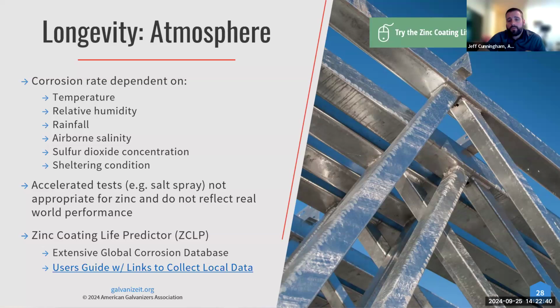We don't have to worry about salt spray testing. Salt spray testing doesn't actually reflect real world performance because it doesn't allow that zinc patina to develop. And the zinc patina is critical in that longevity for the hot dip galvanized steel. So when you're salt spray testing, it's not going to accurately mimic hot dip galvanizing in a real environment. So that's why we created the zinc coating life predictor. And this is off of extensive global corrosion data for the last 150 years on galvanized steel.